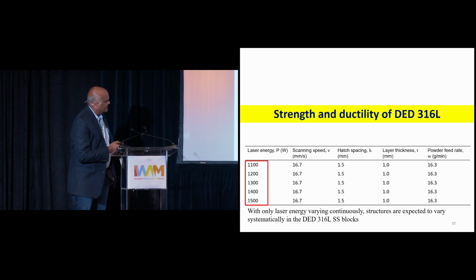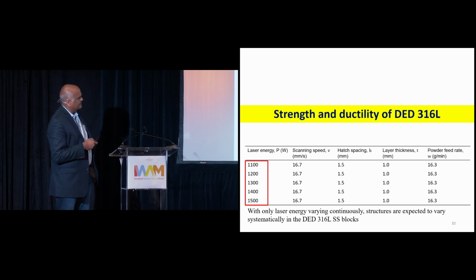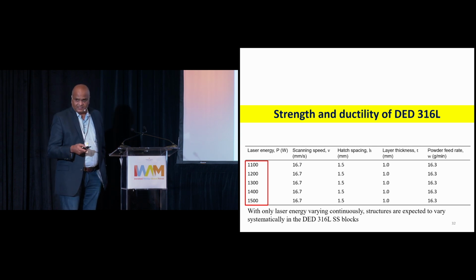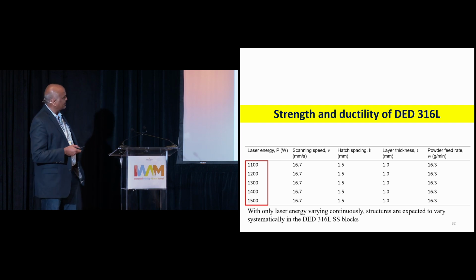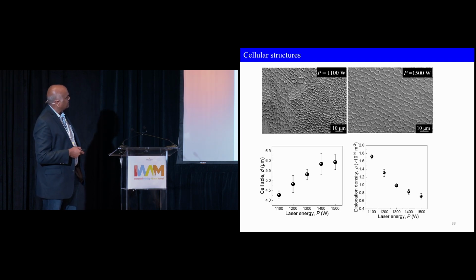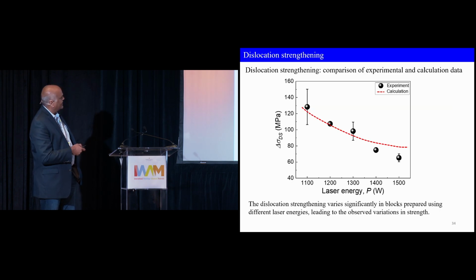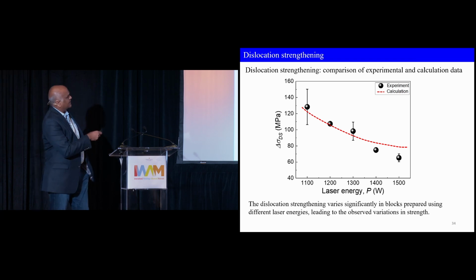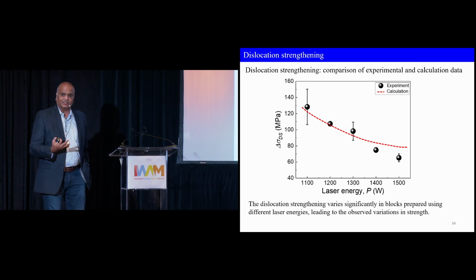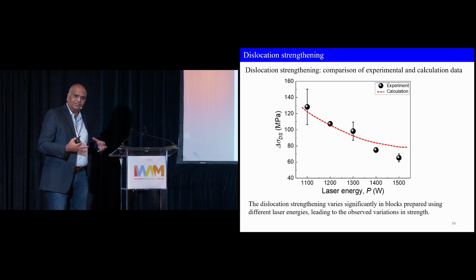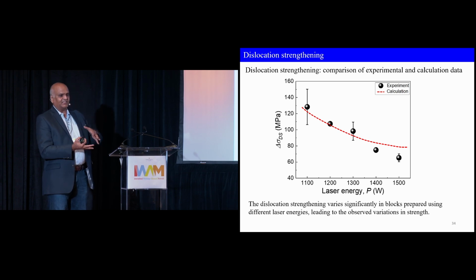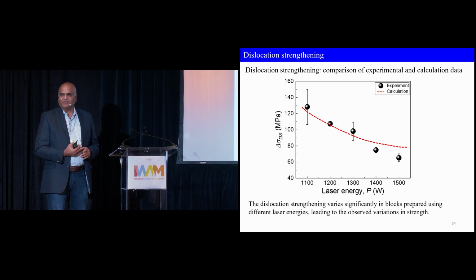So what is the reason that you get high strength? Not the cellular structures, but we did systematic experiments where we can vary these characteristics very systematically. And what we show is that it's all because of the dislocation density. You have the cellular structures, but you also have very high dislocation density in this material, in the as-fabricated state, just because it's going through thermomechanical cycling.